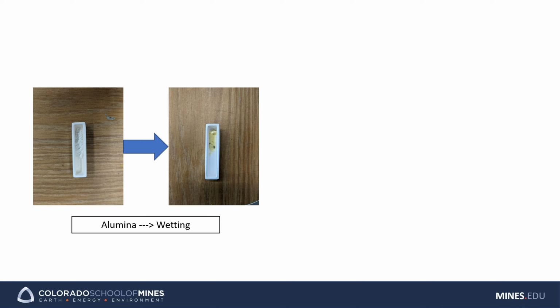And by doing this, they completely adhered to the alumina boat to the point where we could no longer remove the phosphors that we made from our furnace. So basically, they're entirely stuck there. There's no way to remove them whatsoever without a massive amount of effort and heat and mechanical stress, right? So that's not really ideal if we want to make a ton of these powders and really scale it up.